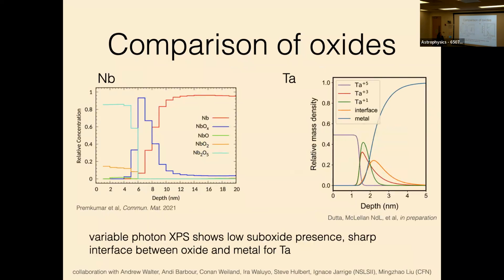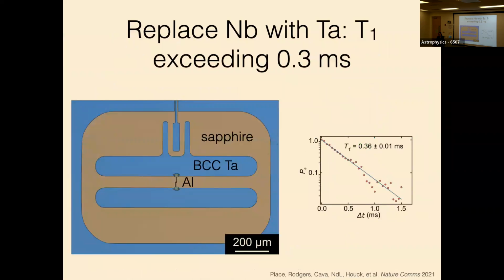And we can even compare these things directly by doing things like variable photon XPS to build up a depth profile. This was some nice work done by Andrew's group in collaboration with some folks at Brookhaven National Lab, where they could see that in niobium, depending on exactly how you prepared it, you got all these crazy oxides that penetrated very deep into the interface, and it was just a big mess. Whereas in tantalum, everything is sharply confined to this little 0.5 nanometer thick layer, and you really mostly get Ta2O5.